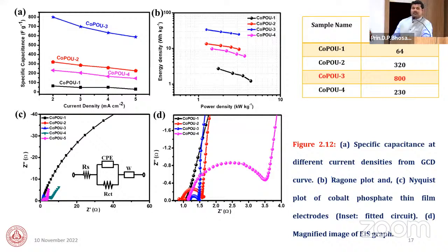I calculated the specific capacitance of this material using the charge discharge study, and the specific capacitance is 800 farad per gram at a 2 milliampere per square centimeter current density. So I calculated energy density and power density of this single electrode. Actually, this energy density and power density is not normally calculated for a single electrode. It's just calculated for this purpose.